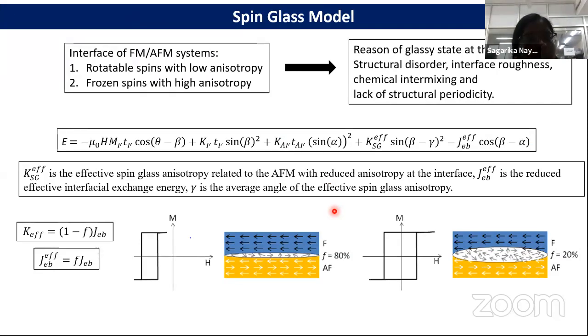In the spin glass model, the interface of the ferromagnetic and antiferromagnetic systems contains both rotatable spins and frozen spins. Rotatable spins have low anisotropy and can reverse during the magnetization reversal of the ferromagnetic spins. However, the frozen spins pin the ferromagnetic spins and try to keep them along a particular direction. The reason for this glass at the interface is interface roughness, disorder, chemical intermixing, and structural defects. This is the energy expression used in the spin glass model, with an effective interfacial exchange coupling because of the spin glass like frustration at the interface, with an effective spin glass anisotropy.